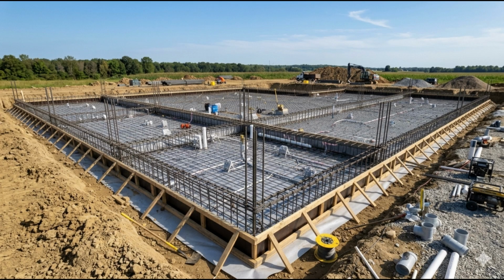12,350-1. The fresh concrete was sampled at the point of discharge, placed in 150 mm steel cube molds in 2 layers with compaction by tamping rod. The surface was struck off level, and the molds were covered with polythene and left to cure for 24 hours before demolding. The cubes were then immersed in water at 20 degrees Celsius until the required testing age.